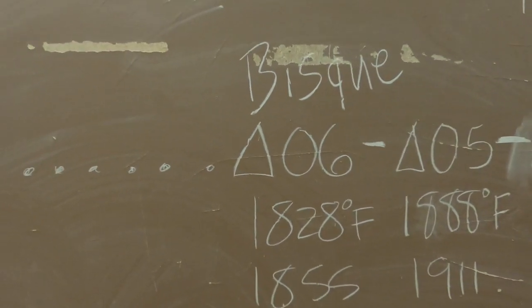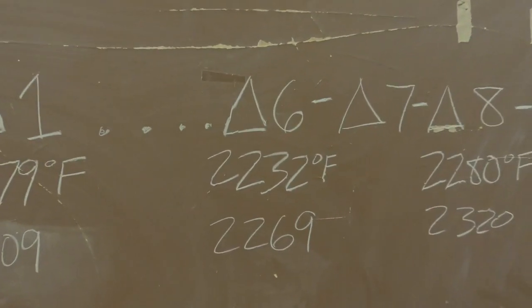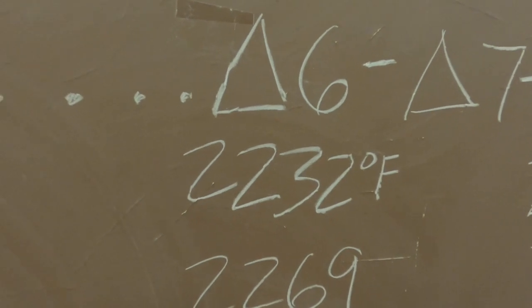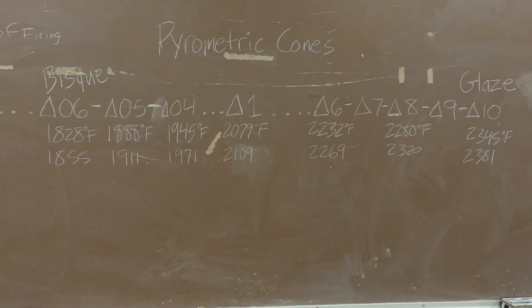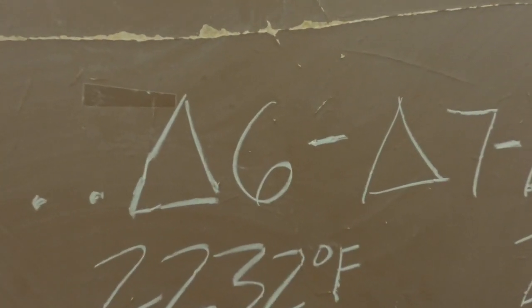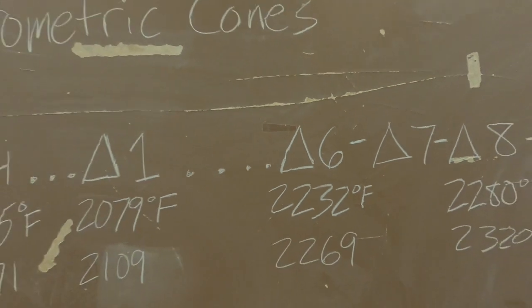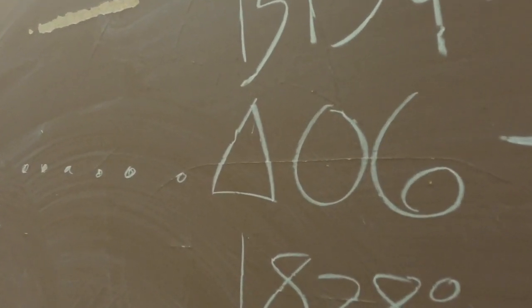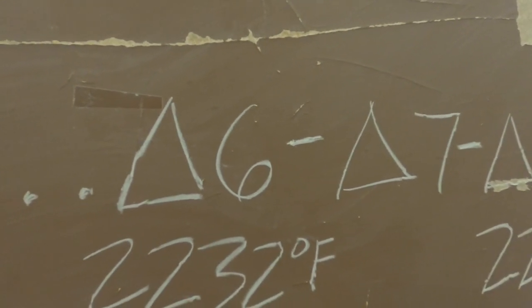The difference between cone 06 and cone 6 in temperature: cone 06 is at around 1828 degrees Fahrenheit and cone 6 is all the way up at 2232 degrees - a 400-degree difference. That might not sound like much, but 400 degrees difference in a kiln firing makes a big difference. If you were to take clay meant to fire at cone 06 and fire it at cone 6, it'll melt into a puddle and maybe even become shiny like a glaze and turn to glass.